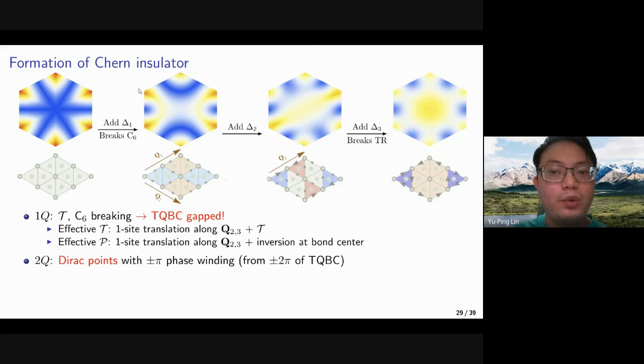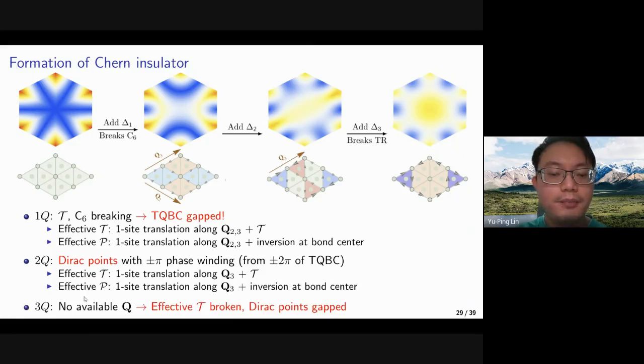If we introduce another Q, it will gap out the nodal curve. So now there are 2 Dirac points here, and equivalently here and here. And these nodal points have the plus or minus pi phase winding, which are inherited from the plus or minus 2 pi quadratic band crossing. We still have the effective time reversal symmetry and also the effective inversion symmetry. But if we introduce the third Q, we no longer have this kind of one-site translation. So the effective time reversal symmetry is broken, and we gap out the Dirac point. In this case, if we gap out the Dirac point by breaking the time reversal, as we saw previously, we are having the Chern insulator as in the Haldane model. And this is the origin of the Chern insulator from the 3Q imaginary order.